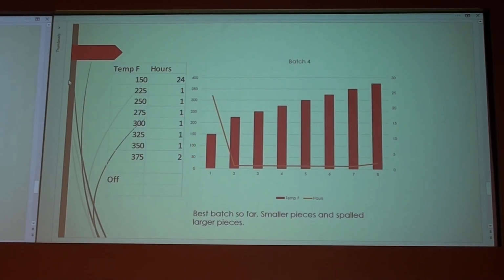Batch 4, all I did is went up to 350 or 375 on that one. I still did a lot of low heat at the beginning to drive off the water, but I only went up to 375 on that one. And then I shut it off and I let it just cool naturally. The sand really holds the heat a long time. I can leave it overnight and I stick my hand in there in the sand and it's too hot yet. So it does cool more slowly.